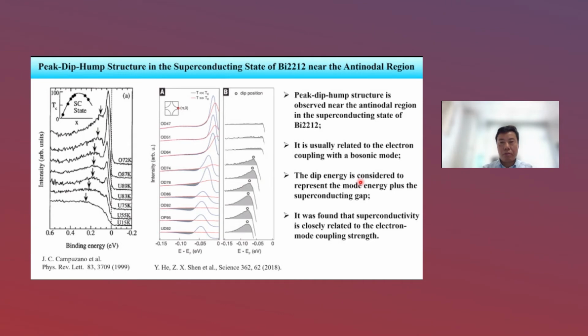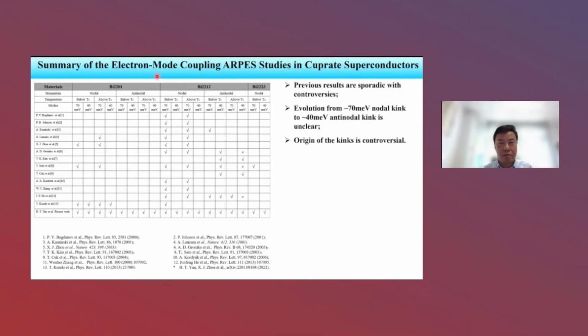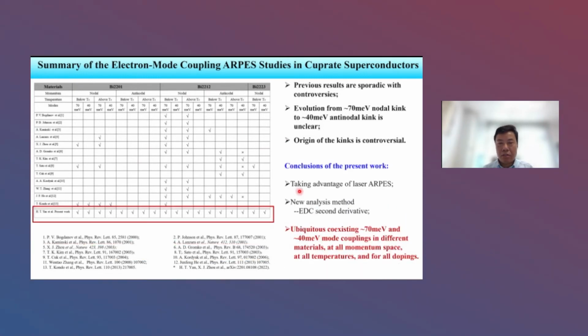Okay. So if we summarize all the previous electron coupling ARPES studies, we can find that in different materials, in nodal and antinodal regions, below Tc and above Tc, there are 70 millivolt and 40 millivolt modes, but the previous results are sporadic, and the origin is controversial, and how the nodal 70 millivolt kink evolves into the 40 millivolt kink is unclear. In our study, I'll just give a conclusion here. In our case, we see that the 40 millivolt kink and 70 millivolt kink coexist in different materials, in different dopings, at different temperatures, actually in all materials. It's really ubiquitous.